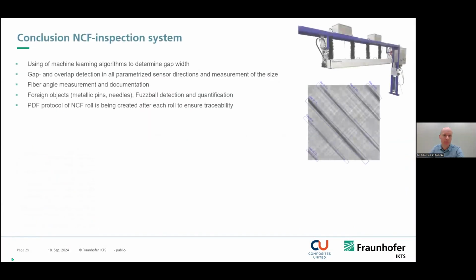We measure the fiber orientation on the fabric, and therefore we use the standard 2D Fourier transformation. And here we see a typical report out of the machine, the orientation for each segment. Yeah, so short conclusion, we're using also machine learning algorithms to determine the gap width. So that's the most important thing for the machine. Gap width in 0, -45, +45, 90-degree orientation. That's a short example.